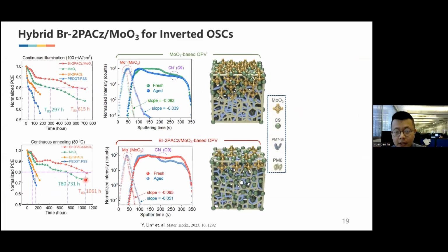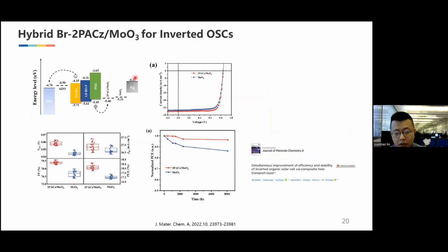We then tried to use ToF-SIMS to detect the distribution of the donor, acceptor, and molybdenum oxide in the OPV device. As you can see, the molybdenum oxide, after the stability test, moves into the photoactive layer. But with the bromide 2PACz, it can partly block the molybdenum oxide from diffusing into the photoactive layer. Also, because the bromide 2PACz can change the surface energy, after aging, the distribution of the donor and acceptor is more homogeneous as compared to the molybdenum oxide based device. Other groups also tried 2PACz with molybdenum oxide and showed a similar conclusion to ours: increased VOC and increased stability.